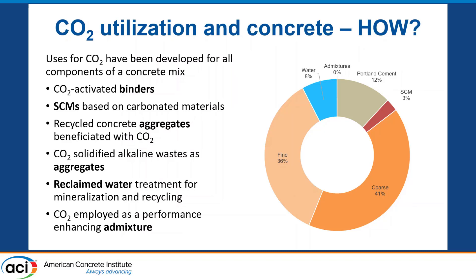How are you using CO2 purposefully in cemented concrete production? There are actually ways to do it in all the different elements of a concrete mix. Most of it is aggregates, and you can turn towards solutions dealing with recycled concrete as aggregates, or solutions that make aggregates from alkaline wastes and CO2 to make hand-made limestone aggregates. You can have SCMs based upon carbonated materials, binders replacing Portland cement that are activated by CO2, and some of our work involves using CO2 as an admixture or as part of the water put into the concrete.